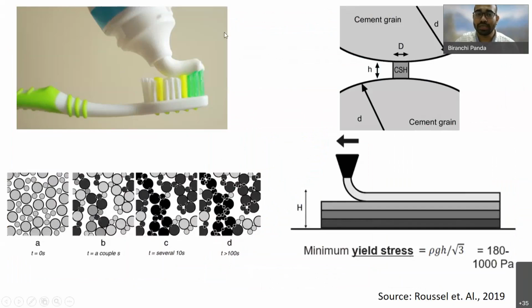So we also use the concept of thixotropy. So what is thixotropy? It is a phenomenon of fluid flow. If you know this example, early morning, when you press the tube, the paste comes out of the tube very easily. You don't have to press very hard to get the paste out. So we need very little pressure, but once you deposit the material on the brush, it remains in its own position. It neither spreads away nor is it difficult to squeeze out. So it means this material has thixotropic property.